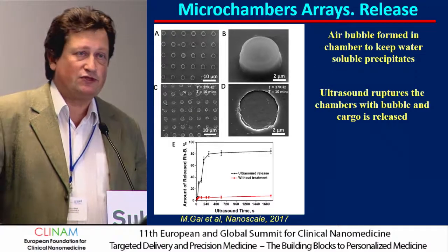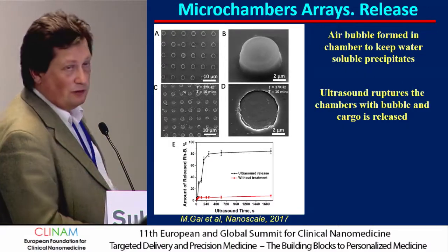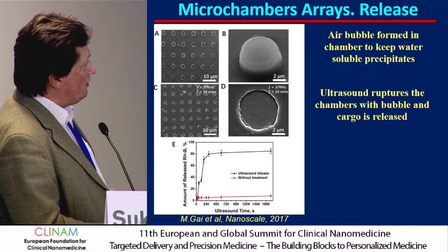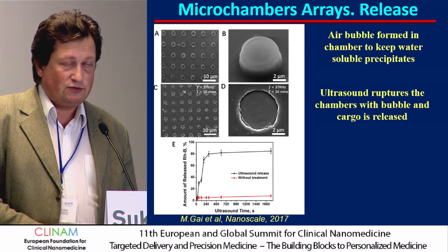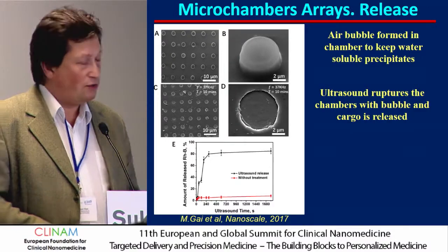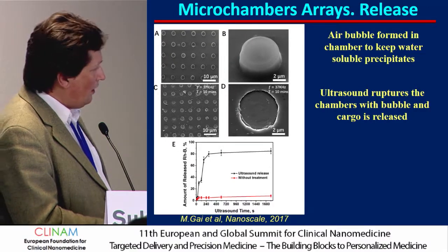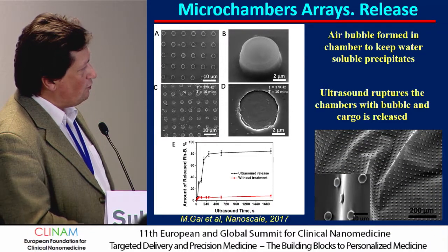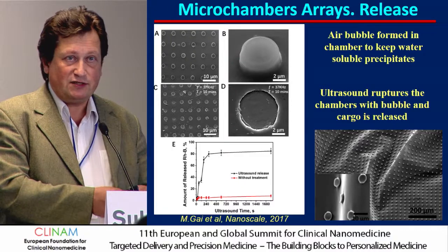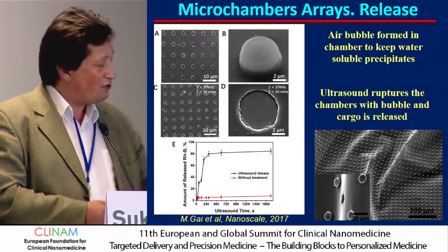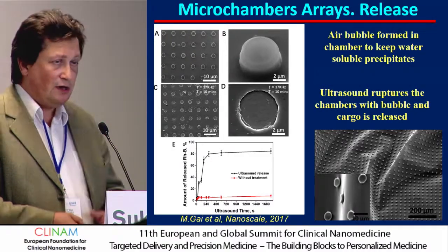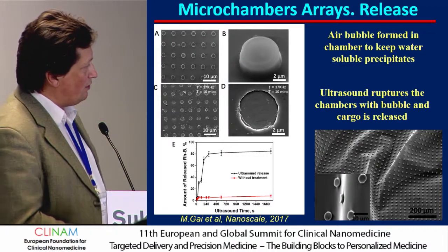And what is the most sensitive to the air bubble? It's ultrasound. If you apply ultrasound, for instance a focused ultrasound, whatever area is subject to the focused ultrasound, you blow up your chambers, and your precipitates will be dissolved. So you could make those films freestanding. You could put it under, for instance, operation. You could put it there, and either it will be just degraded over a longer time, or you could stimulate those releases.